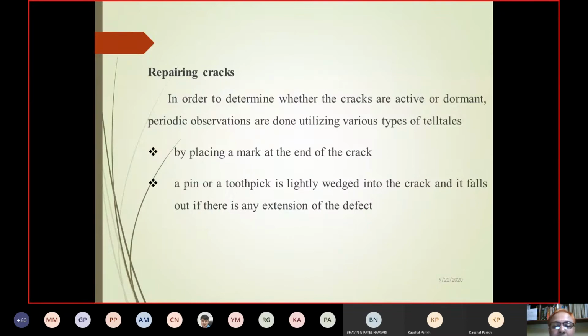Then repairing cracks. Now, how to repair the crack? By placing a mark at the end of the crack, a pin or toothpick is slightly wedged into the crack, and if it falls out, there is extension of the defect. Check whether it is a live or dormant crack.